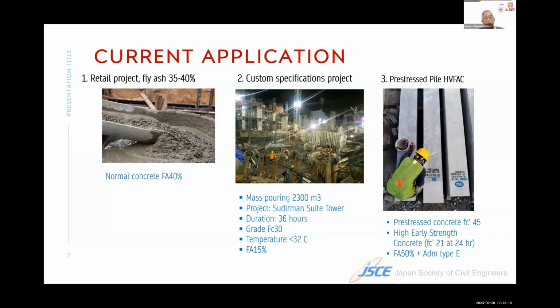So in this condition, we do material engineering by adding chemical admixture. So for this product, we use superplasticizer and accelerator, because we have to reach the strength of 21 megapascal before 24 hours.